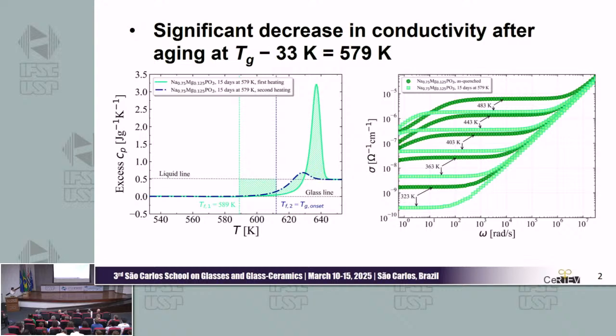In the left graph, you see how the effective temperature changed after relaxation. It changes a lot for this glass. This is a mixed modifier glass. And related to this, all the properties change. In this case, the ionic conductivity. You see it measured at different temperatures. And it changes almost 1 order of magnitude for the same glass.